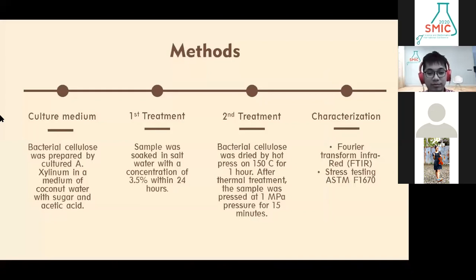We chose static culture as the culture method. The medium we use is coconut water with sugar and acetic acid, and Acetobacter as the bacteria. The medium was boiled and stirred for 1 hour, and we cooled it until it reached room temperature. After that, we poured the Acetobacter into the medium solution, which was inoculated for 14 days. After 14 days, we harvested the bacterial cellulose, and it was soaked in salt water with a concentration of 3.5% for 24 hours.